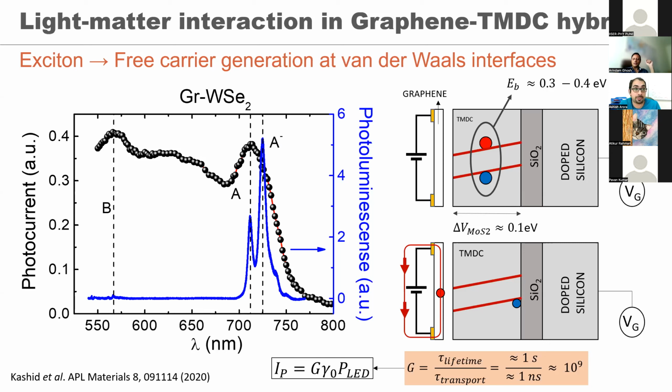That would be some femtoseconds? Tens of femtoseconds. Oh, wow. Tens of femtoseconds. That explains it. And this has been shown in pump probe spectroscopy as well as from calculations. Although I'm not particularly confident of the calculations, it's still not very clear why the timescales are so short. But at least the pump probe spectroscopy shows that the transfer timescales are in the order of a few tens to 200 femtoseconds, which is about an order of magnitude or a little bit more shorter than the exciton recombination.